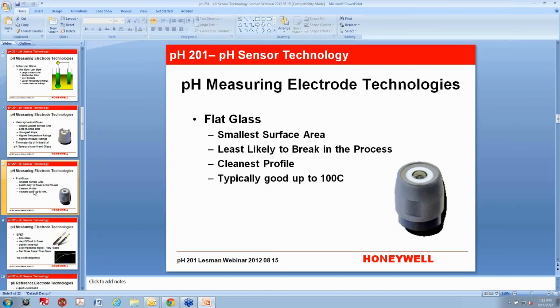Unfortunately, it has a smaller surface area, obviously, because now we're down to a disc instead of a hemisphere or a sphere. But it is the least likely to break in your process because it's not hanging out. It has a flush profile with the liquid junction and the body of the sensor. I would also consider it the cleanest profile because it doesn't have anything sticking out that your process may tend to coat up on. So it's not going to get coated up usually as quick as a hemisphere or a spherical glass.